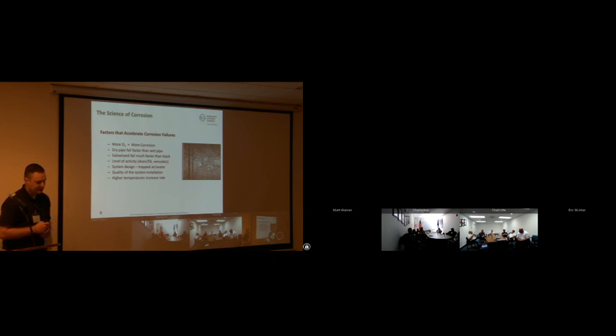And this is the really interesting one. Higher temperatures increase corrosion. So corrosion is just a chemical reaction, and any chemical reaction is influenced by temperature. The higher the temperature, the faster the reaction. So a general rule of thumb in chemistry is 18 degrees Fahrenheit. An increase of temperature of 18 degrees Fahrenheit is going to double your reaction rate. If you go 18 degrees, you're double. If you go 36 degrees, you're quadruple. If you go another 18 degrees, you're going to be 8 times the corrosion rate you were at room temperature.